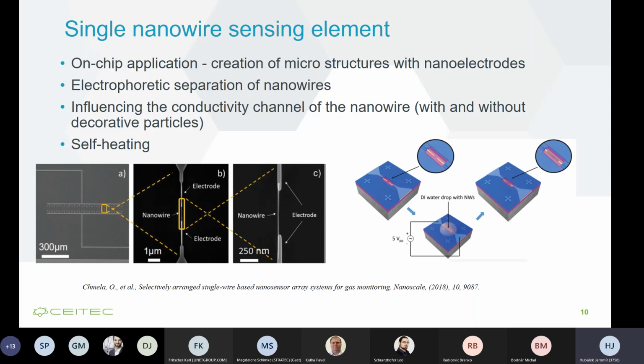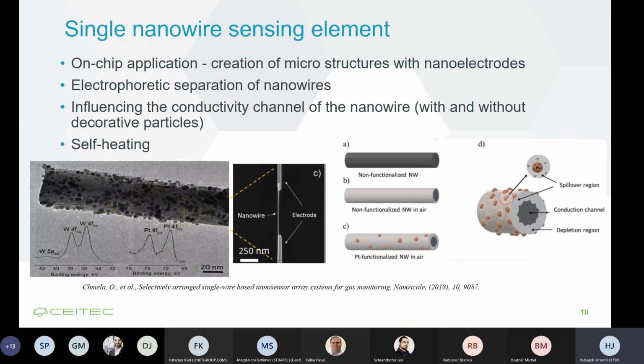And this single nanowire was deposited by electrophoretic separation. And we measure in the gas. For example, we decorated nanowires and compared with undecorated, as you can see in this picture. So we have some results with this type of nanowires where the selectivity was increased, because probably you know that the selectivity is the problem in this case of semiconductor